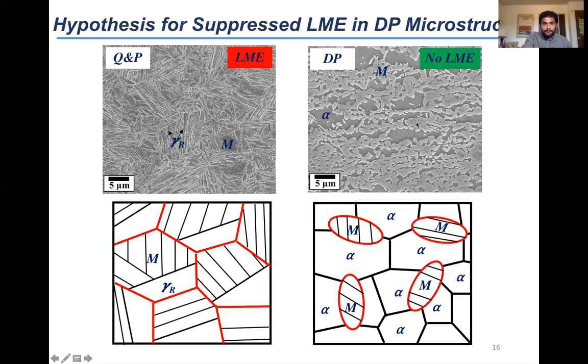Now, upon cooling, the martensite formed inside of the austenite grains in both the steels. So here is the martensite in the QNP steel, here is the martensite inside the DP steel. The red is the prior austenite boundary, and what do we see? The prior austenite boundaries are well connected and have a larger area fraction in the QNP steel. In contrast, in the DP steel, the prior austenite grain boundaries have a smaller area fraction, and on top of that, the boundaries are not well connected. Now, these prior austenite boundaries are responsible for the LME crack, and it is present as a continuous network in the QNP specimen, which helps the LME crack to form. And in case of the DP steel, they are present in a clustered format here and there, and therefore they do not allow the LME cracks to form.